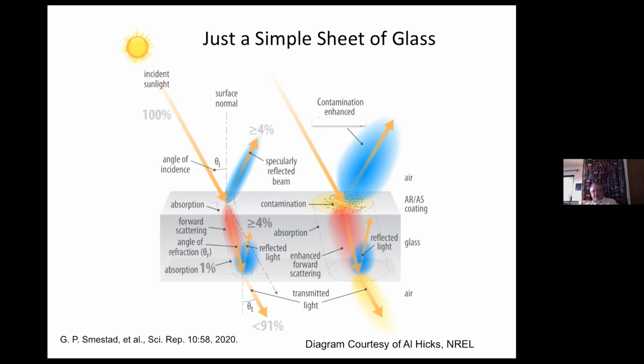The plots that I was showing you before is a very simple experiment that students can do. Take a piece of glass, put it outside, let it soil, and measure the transmission as a function of wavelength with a spectrophotometer. I hope that you do this because you can get a very good idea of what the soiling is. If you have a CSP system, you could instead use a mirror here, where this back surface would be an aluminum or a silver mirror. But in this case, the same. You would measure the reflection as a function of wavelength. And again, this diagram is in the Scientific Reports paper.